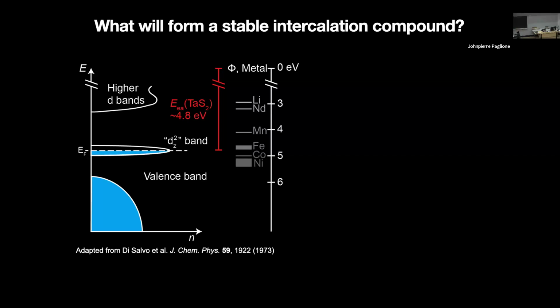So we can just look at the electron affinity, and for the niobium and tantalum chalcogenides, the orbital parentage of the band crossing the Fermi level is predominantly dz squared, at least at gamma, and it hybridizes with other orbitals, but it's predominantly dz squared. For a very crude estimate, we could think of that as the dz squared band, and it's partially filled, so that tantalum and niobium sulfides and selenides are all metals. And so the question is, how much does this want an electron versus how much does the transition metal ion that we want to react with it want to give up?